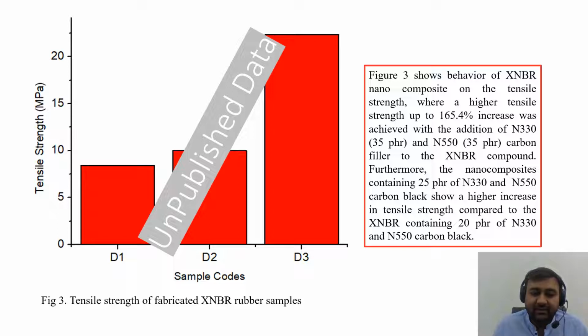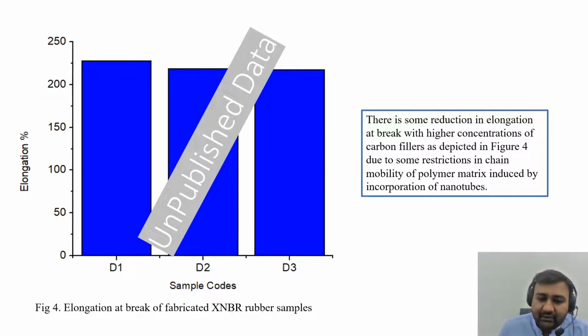So this figure shows the tensile strength of fabricated XNBR rubber samples. The sample with the highest tensile strength, which is sample D3, shows a 165% increase in the tensile strength with the addition of the carbon fillers. So these are the results of the elongation at break of fabricated XNBR rubber samples. There is some reduction in the elongation at break with higher concentration of carbon black fillers, as shown in the figure, due to some resistance in chain mobility of the polymer matrix induced by the incorporation of the nanofillers.